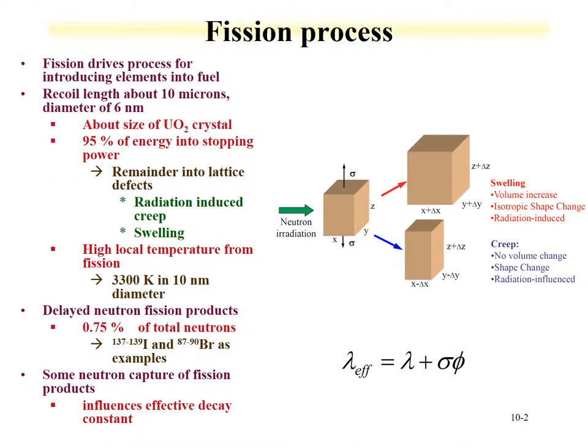The fission process is necessary in reactors for the production of heat and ultimately electricity. It is also the source for introduction of other elements into the fuel, whether fission products or actinides through capture. Fission products will recoil about 10 microns in UO2 with a diameter range of about 6 nanometers, so there is very little straggling along the width of this recoil. This happens to be the size of a UO2 crystal. Frenkel pair production and defects will be formed, with some effects on materials.